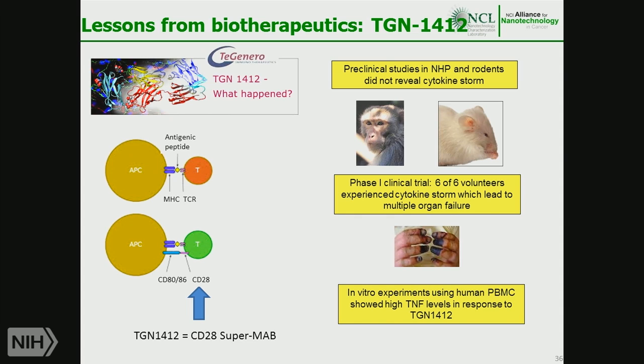Interestingly, then these studies were stopped and the material was investigated. It was found that this material passes all pyrogenic tests in terms of LAL. It was not endotoxin, and there were no chemical or biological contaminants in this material, but the material itself induced cytokine storm in vitro. Normal human PBMCs, peripheral blood mononuclear cells, were used as a model. Apparently, non-human primate and rodent models were insensitive to this change.